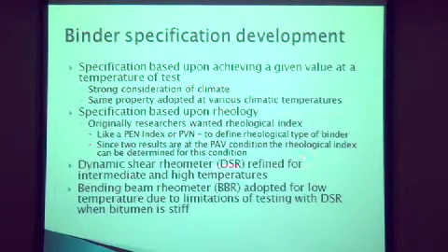The dynamic shear rheometer was basically a piece of equipment that was already in existence at the time of SuperPave. It was refined, it was improved, and it was adopted for the intermediate and high temperatures. The bending beam rheometer was adopted for the low temperature due to the limitations you have with a DSR of testing those bitumens when they're very stiff. So a bending beam rheometer does a better job at evaluating the stiffness or the rheology of the asphalt binder at those low temperatures, or when the material is behaving in a stiff manner.